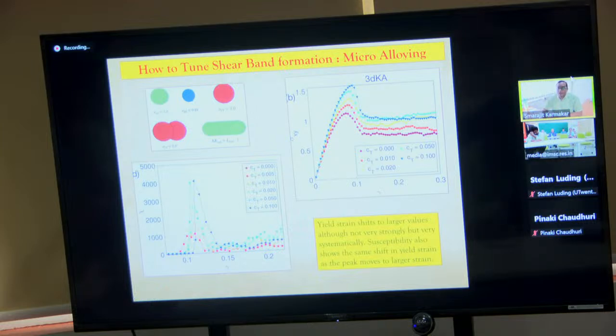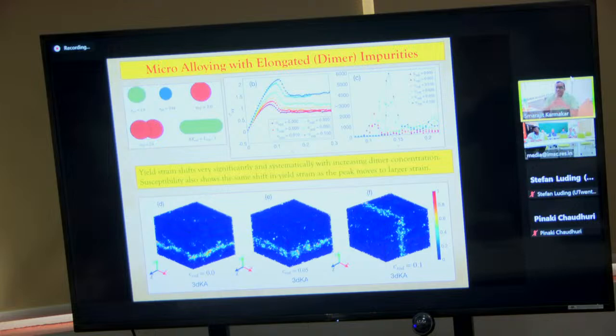And then we went on with the idea, instead of using a large particle, we thought of introducing an elongated particle to see whether they can be better pinning sites, because a long particle will have various dynamical restrictions in terms of both translation and rotation. Particularly in rotation, they won't be able to rotate as freely as a spherical particle. So this is what we looked at in this scenario. We took a system and introduced dimers. And when you increase their concentrations, what we see is that